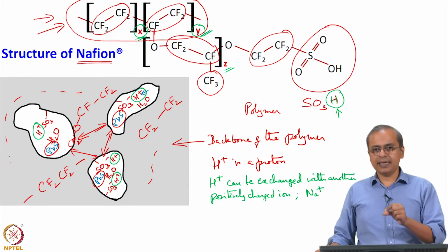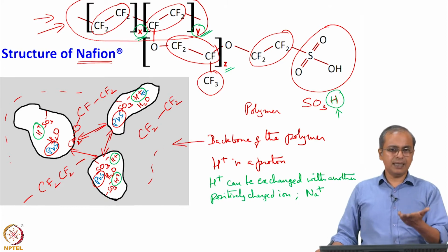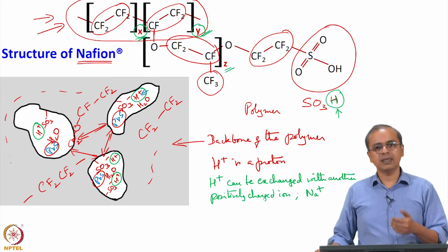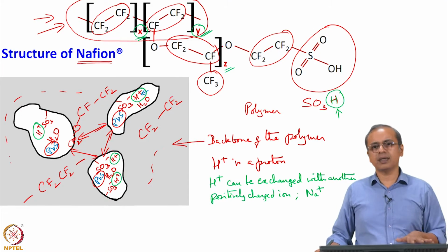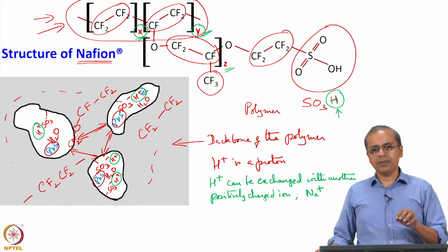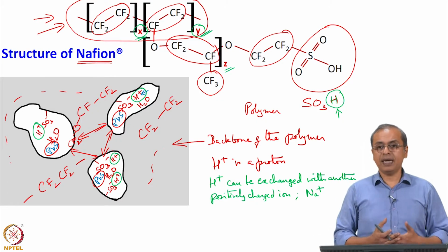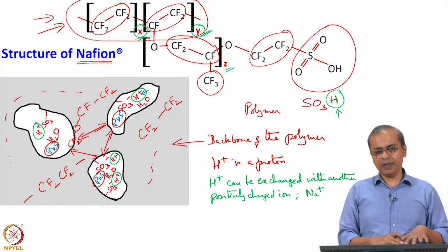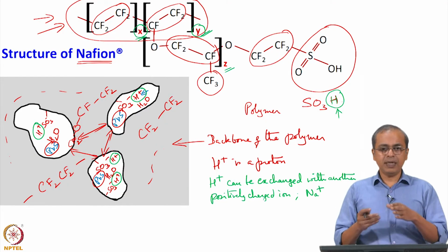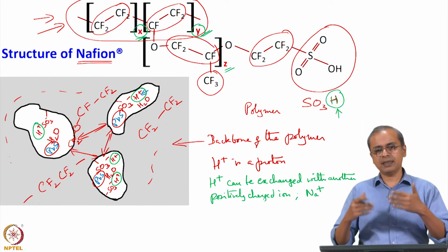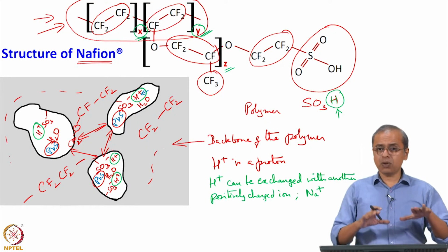Maybe the only drawbacks that I can think of are, number one, that because fundamentally it is a polymer, it restricts your temperature range of operation, and number two, it means there is only a dilute presence of the nanoparticle, because you are going to have mostly polymer and here and there the nanoparticle. So, if you want a very high concentration of nanoparticles, this may not be very useful for you. But if you just want a film which has those nanoparticles and can be used for any other application, you can do that. And this film is also mechanically stable.